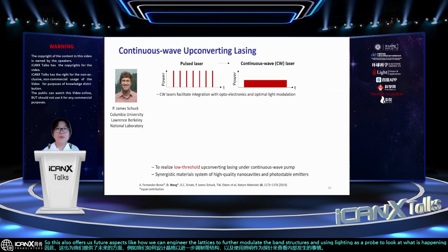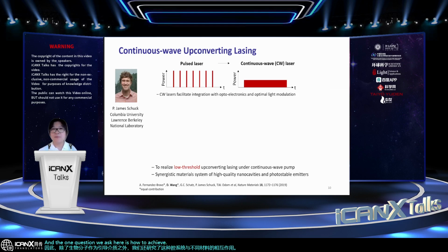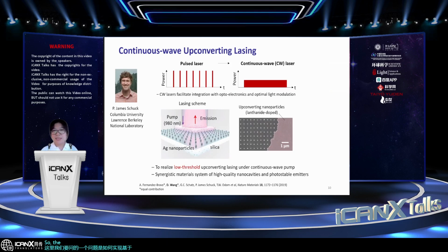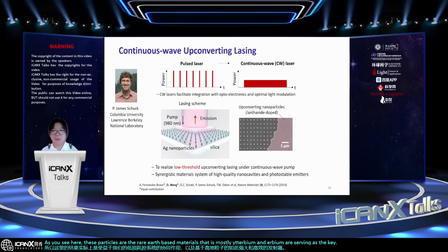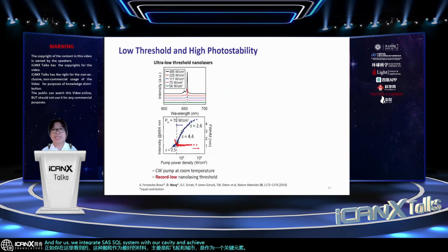Beyond dye molecules as a gain medium, we also look at interactions of this cavity system with different materials. One question we ask here is how to achieve a low threshold laser based on a continuous wave pump. The result here benefits from the synergy of our low-loss cavity system and a robust and efficient emitter based on upconversion particles. As you see here, these particles are rare earth-based materials, mostly ytterbium and erbium serving as the key elements inside as emitters. And we integrate such a system with our cavity and achieve low threshold lasing at room temperature.